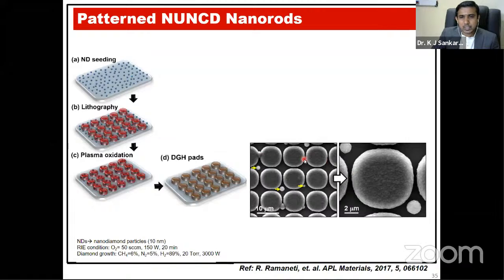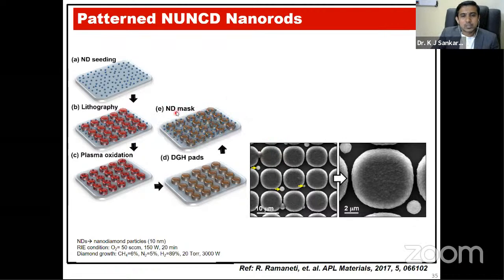So you can see the selective area deposition of a NUNCD film on this silicon substrate. Wherever the plasma oxidation happens, the diamond seeds in between are etched out, and the diamond films were formed only in a circular pattern. And again, we use a nanodiamond mask.